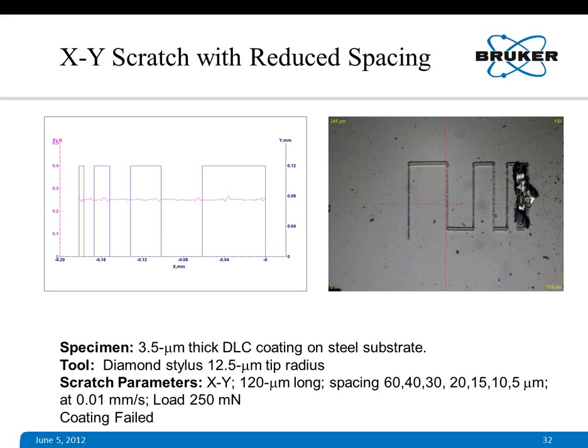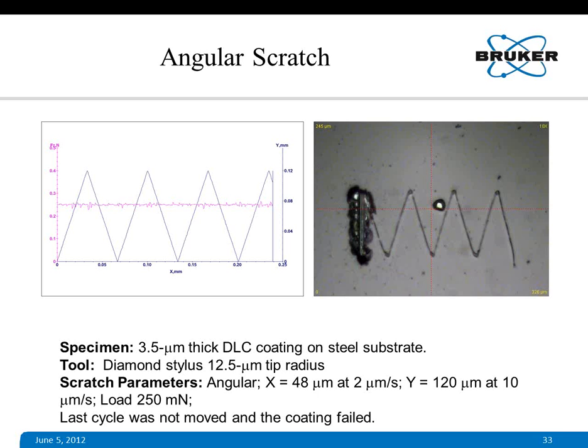This implies that pre-stressing by making a series of scratches has a lot of influence on the failure of the coating by delamination. So for instance, in this case, it fails when the distance of separation between two successive scratches was reduced to 5 microns. We can also perform angular scratches, at any angle. We can write a script to perform this kind of scratch. And again, at the end, when it moved the slider, the coating failed.